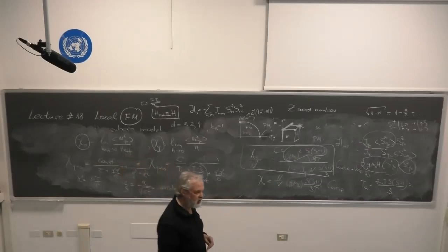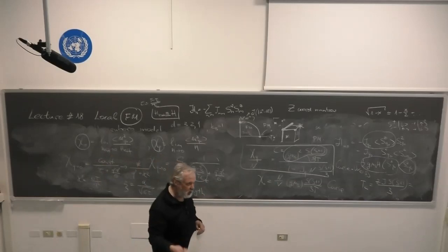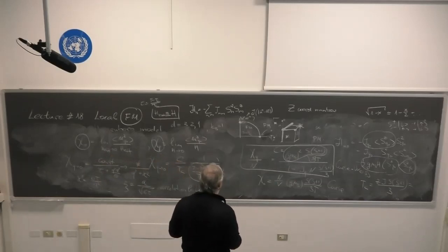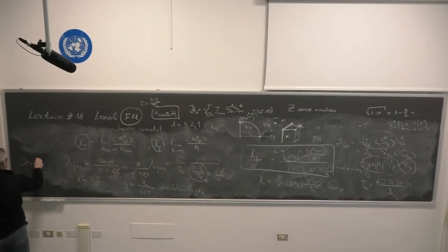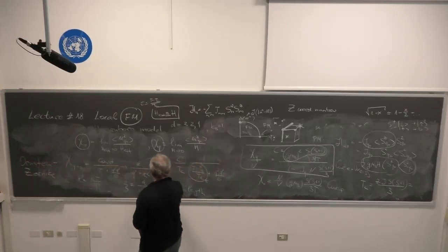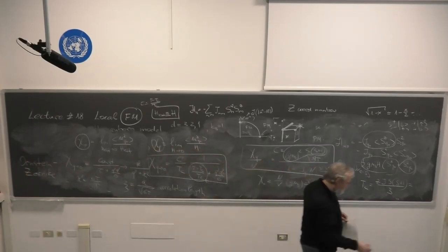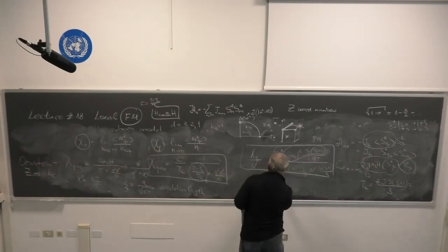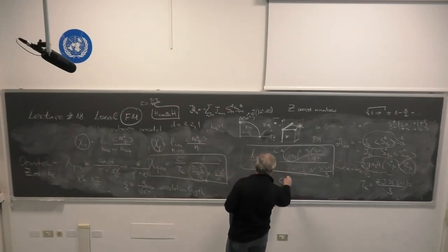The same way as we introduced correlation length in the theory of superconductivity. What we see here is that the correlation length diverges as 1 over square root of tau when you approach the critical temperature. By the way, this form is called Ornstein-Zernike. If we compute the Fourier transform of this correlation function, assuming that the form survives also for large q, we extend this definition for large q, we obtain that chi(r) has the same shape as the screened Coulomb interaction: chi(r) is proportional to e to the power minus r divided by xi, divided by r.